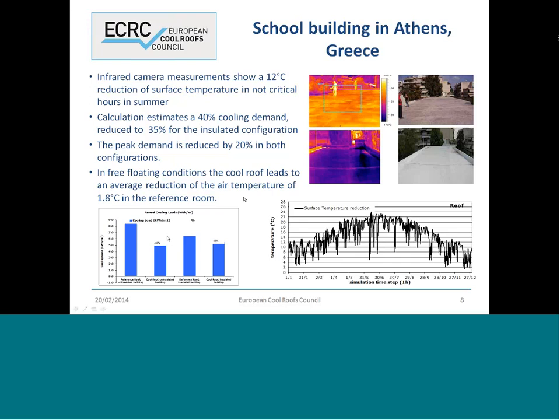This plot here on the right corner shows the reduction of the surface temperature between the cool roof and the original roof through the year. We can see that during the summer period, such difference reached 20 degrees in many hours. This is relevant since a reduced thermal stress in the roof surface increases the lifetime of the roofing system.